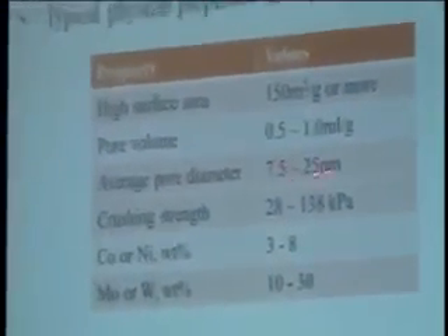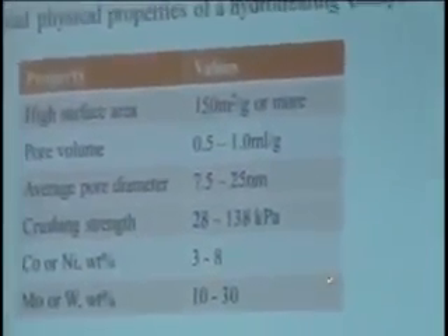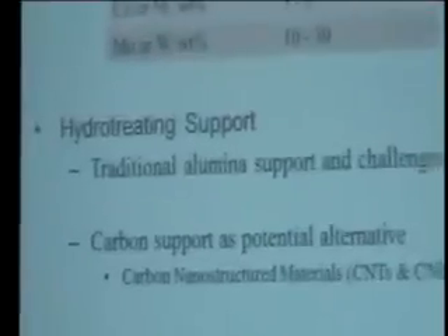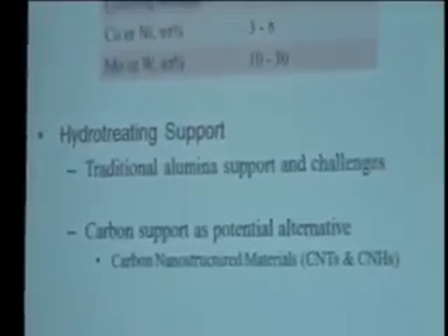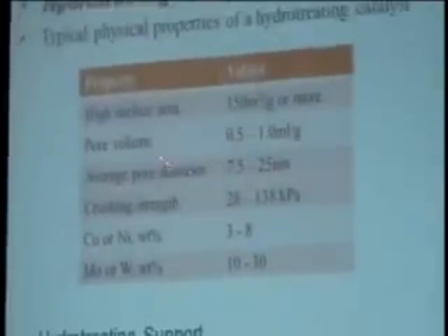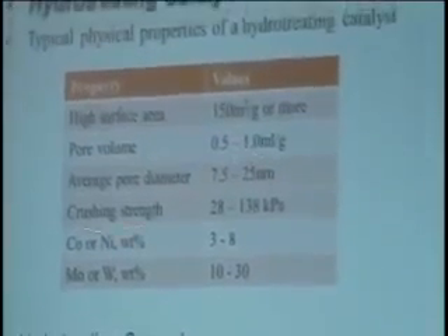So this table shows the typical physical properties exhibited by a hydrotreating catalyst. High surface area of 150 or more is important because it allows the active species to be well dispersed. And then the pore volume within this range, 0.5 to 1, is also important because it allows the capacity for metal deposition. Average pore diameter is within 7.5 to 25 nanometers. For example, for HDS involving smaller molecules, an optimal diameter of 10 nanometers is important.